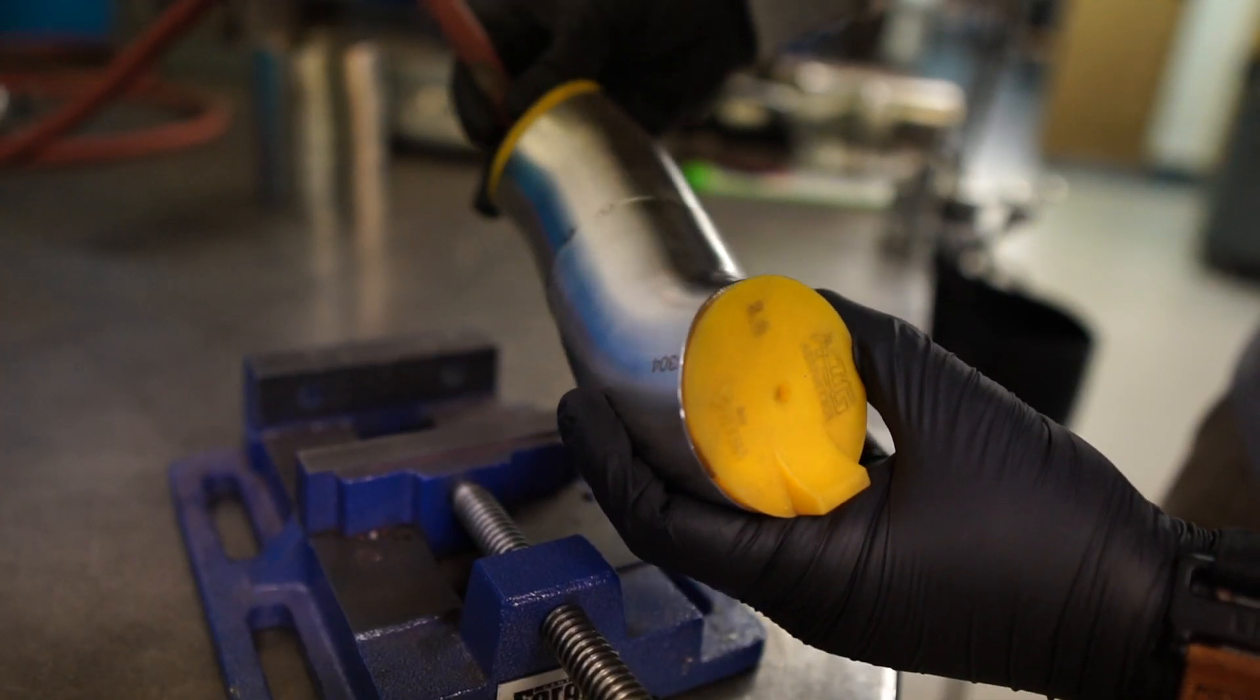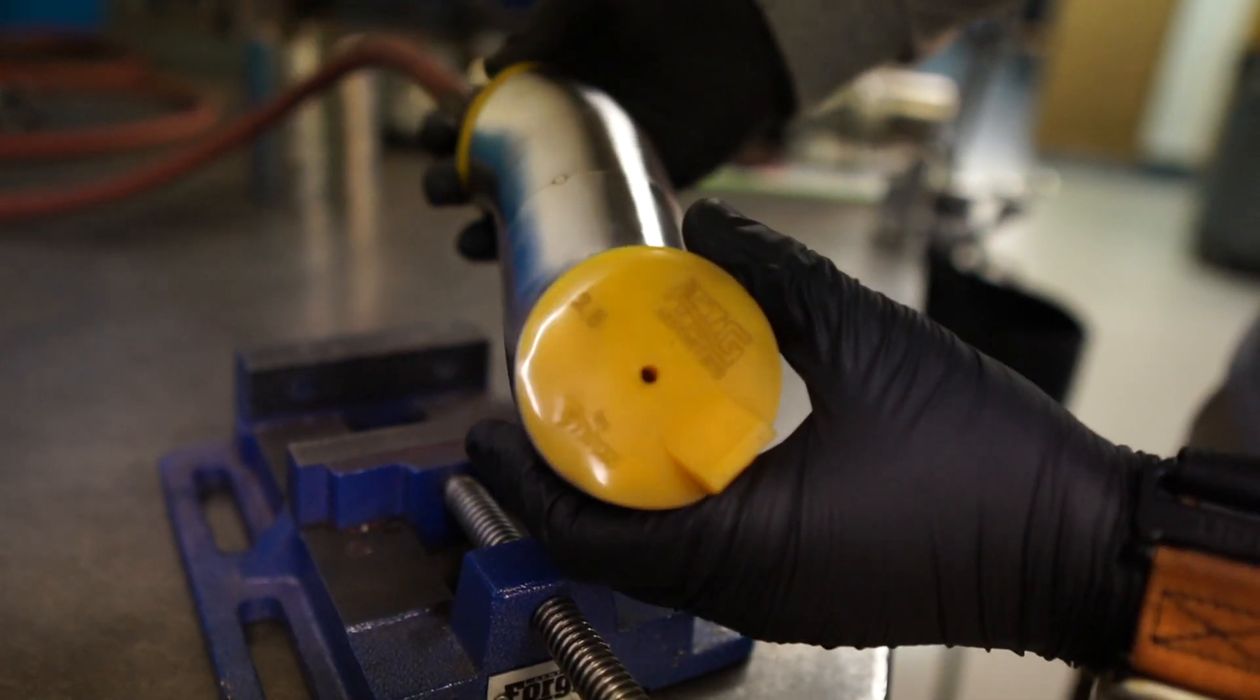Cup size varies on your stainless tube's diameter. Make sure you are back purging all of your parts. For a seamless clean tie-in, start on your last ripple and increase amperage until your toe width of the weld matches the previous weld's toe width and then move forward one ripple and then start adding filler rod.